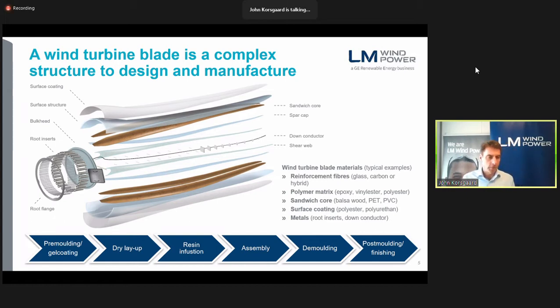On the outer surface, we have the surface coating to protect the blade from wear and tear. And often the blade also has a separate leading edge protection layer, since the leading edge is the most exposed area to wear and tear. Then just after that, we have the surface structure, which defines the aerodynamic shape of the blade. In general, the surface structure is built up as a sandwich structure with biaxial reinforcement layers and a sandwich core. The main load-carrying part of a blade are the spar caps, which consist of unidirectional layers of reinforcement in the blade length. The spar caps in the upper and lower shells of the structure are kept apart by a number of shear webs.